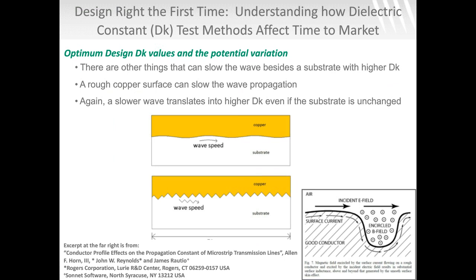And that is copper surface roughness. We have found that if you build two circuits on the exact same substrate, one using smooth copper, one using rough copper, the circuit with the rougher copper will have a longer electrical length and a slower wave. And that's going to be perceived by the circuit as a higher dielectric constant, even though the substrate's the same.